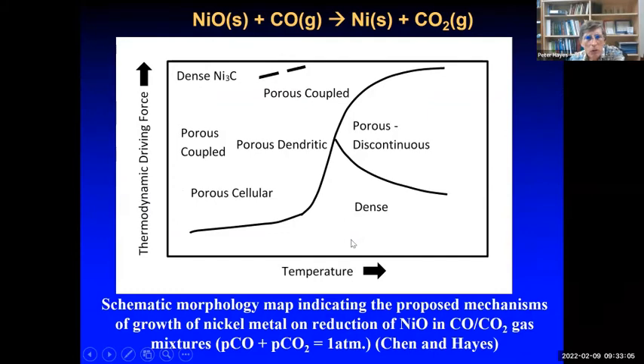So if we can summarize what's going on in this system, you see that we have a region here where dense nickel is formed on the surface of nickel oxide, which, to be honest, is bad news because that stops the reaction completely. At low temperatures, we get the formation of dense nickel carbide. So in this particular system, the thermodynamics tells us that CO reacts with nickel to form nickel carbide at particular CO-CO2 ratio. And so that's why the reaction stopped, because we were forming nickel carbide and not nickel metal.